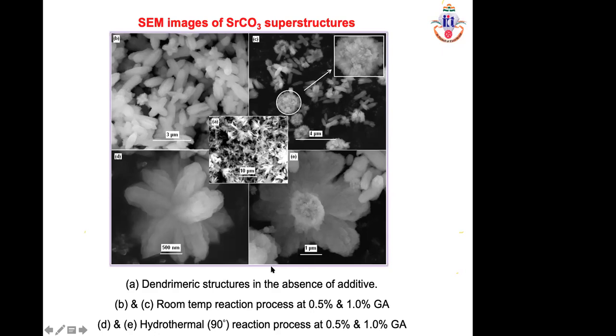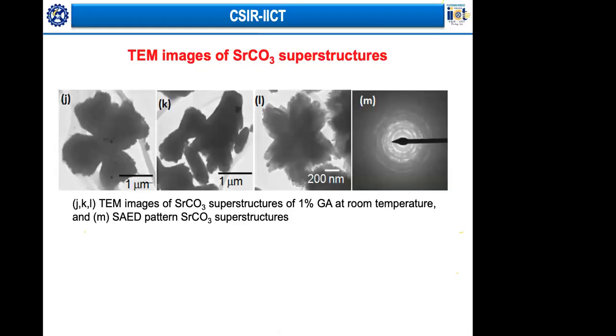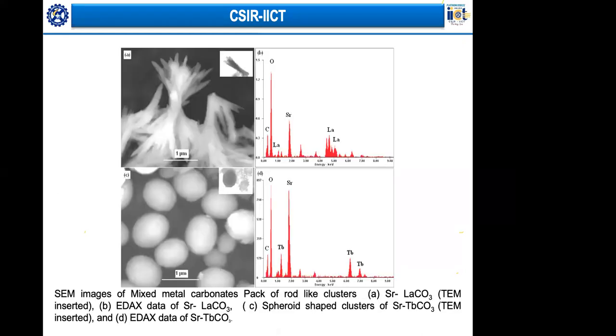So here again, you can see a change in the morphology, like nice rice grains. At a little higher concentration, the growth process is taking a different shape, and that is how it ends up in these kinds of materials. So the same thing in the TEM image. Here again, you can see the formation, and by SAED pattern, we can confirm that it is strontium carbonate and so on. Here again, lanthanum and terbium change the shape of this material. Small dopants of other materials also make a difference. What I mean to say by this is that these reaction parameters are so critical that small changes also influence the formation of these kinds of materials.